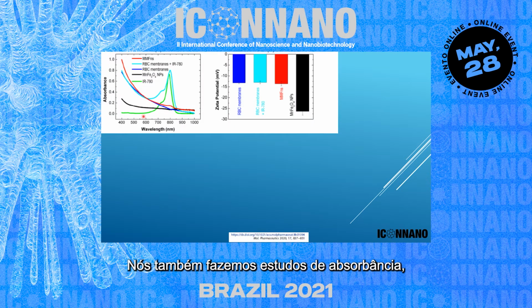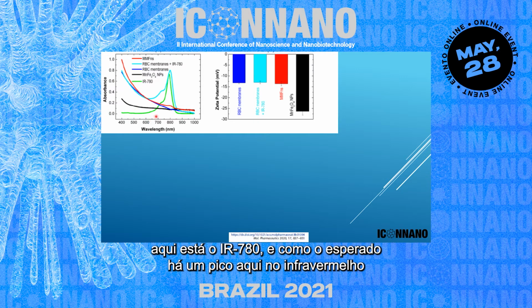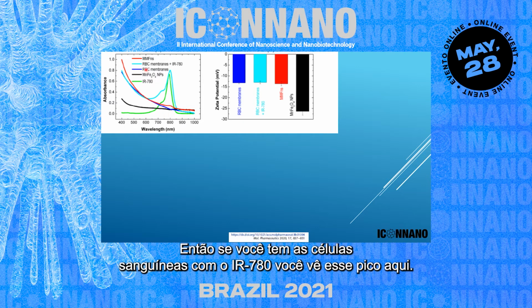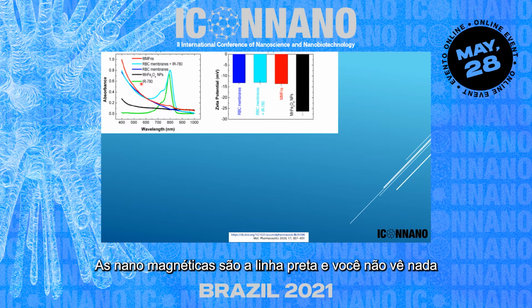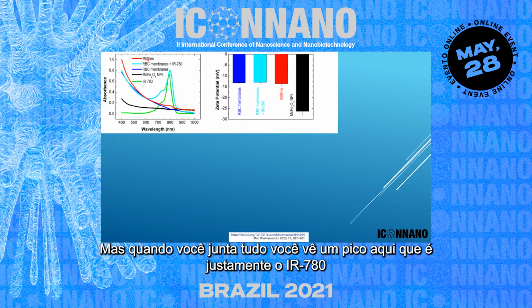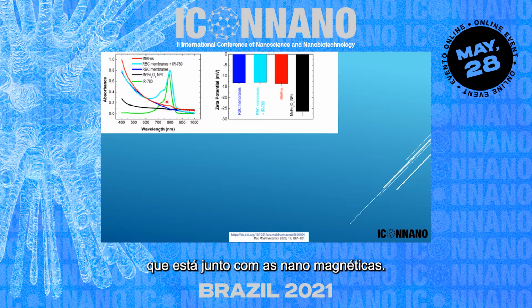We also did an absorbance study. So here it's IR 780. As expected, there is a peak here in this near infrared range. So if you have the red blood cells with IR 780, you do see this curve here. The magnetic nanoparticles are the black curve. You don't see anything. But when you put them all together, which is our sample, you do see a peak here, which is related exactly to the IR 780 that was incorporated together with the magnetic nanoparticles, forming our nanostructures.